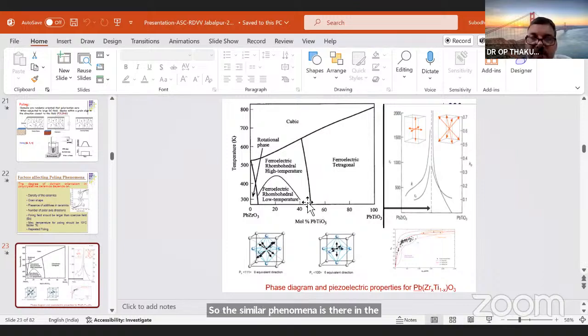So when we take the composition around this boundary, which is called the morphotropic phase boundary, you will find that values like the coupling coefficient and the dielectric constant increase drastically in this region. That's why the morphotropic phase boundary region is exploited for piezoelectric applications. But for pyroelectric applications, where you don't require a high dielectric constant and a high coupling coefficient, you have to choose the composition in the area where the dielectric constant is less. That I am going to discuss in the coming slides.